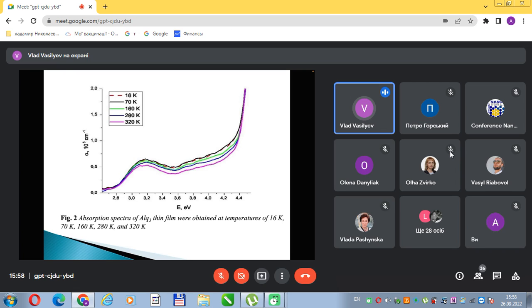to singlet exciton annihilation. The reduction of the exciton annihilation with increasing temperature was assigned to a thermally activated occupation of non-quenchable localized excitation states.